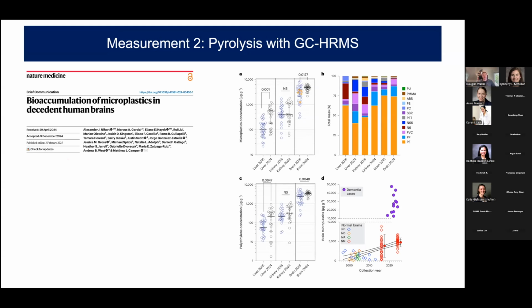And so what they did in this study is they used a pyrolysis-based measurement technique that they applied to different organ systems, and then also looked at the difference between brains from individuals who had Alzheimer's and healthy controls. Now, there were some other methodological issues related to control matching, but one thing you'll see here is that the individuals with dementia had brain microplastic levels that were 2 to 5 times higher than any of the other population.